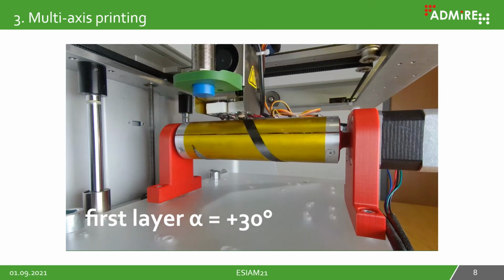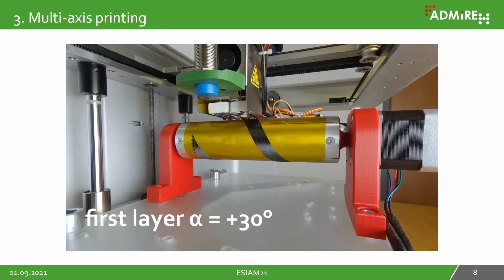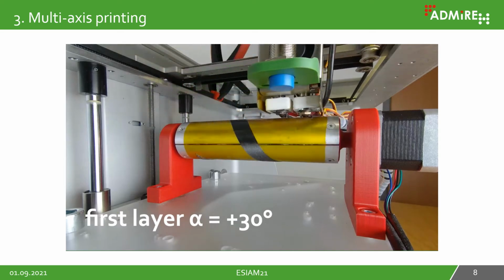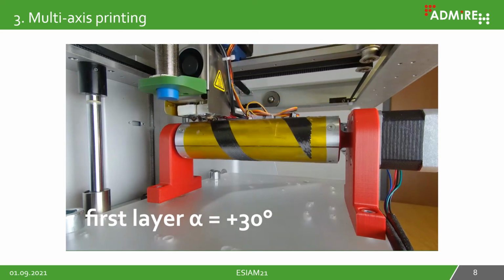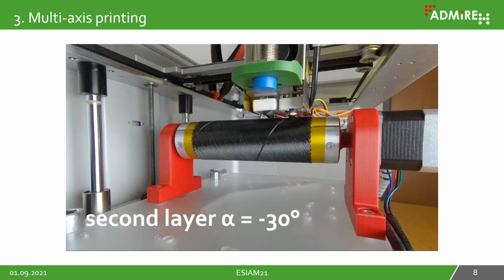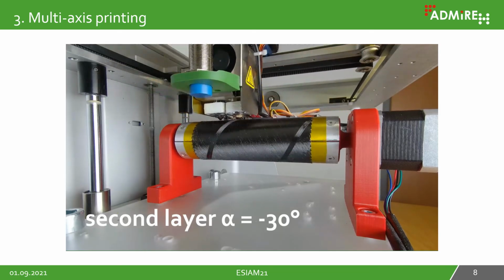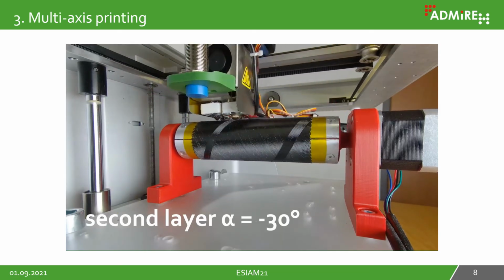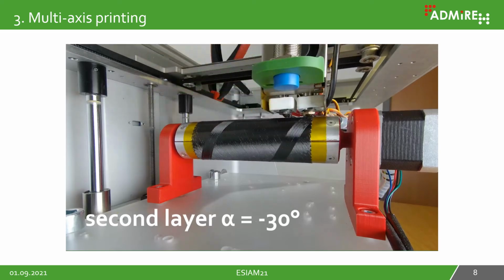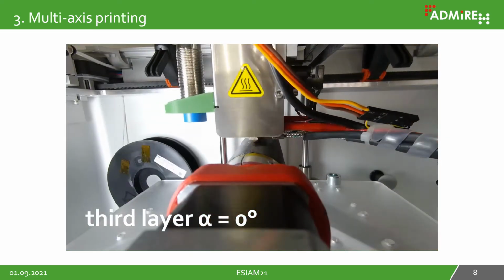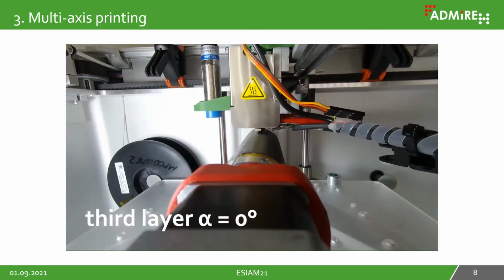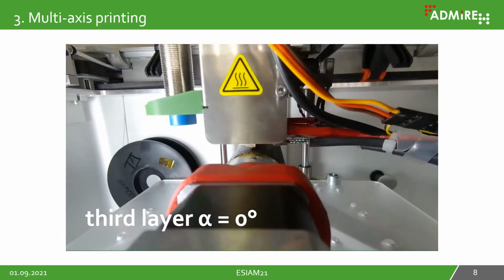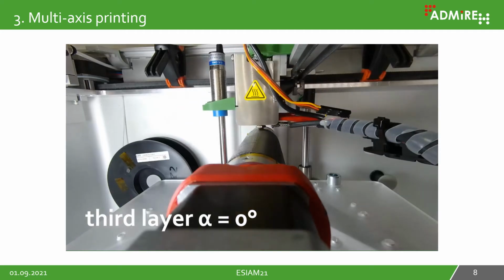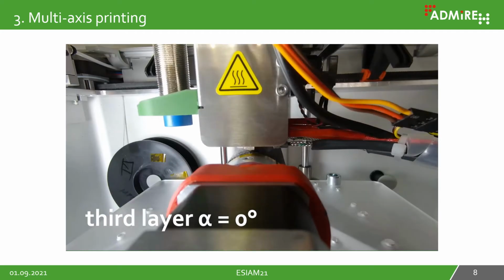To demonstrate our modular axis, you can see the video, and at the moment the first layer of the 30-degree fiber angle is printed. Now the second layer of the 30-degree fiber angle is printed. And after that, the first 0-degree ply is also printed onto the already existing ply layers. The video is sped up, so the process itself takes way longer than shown here.